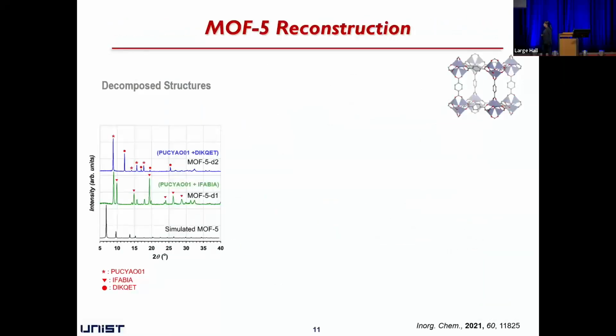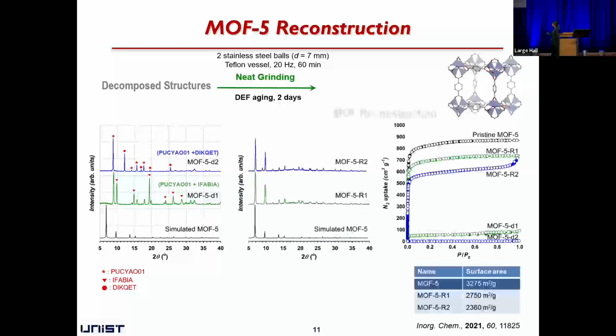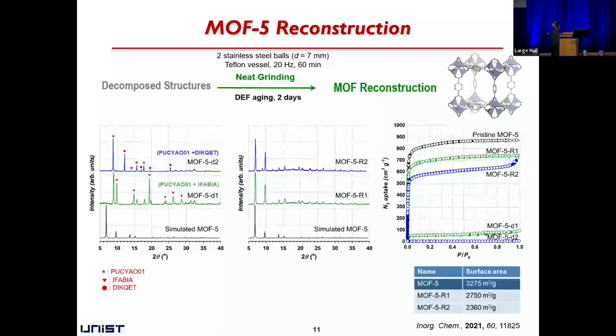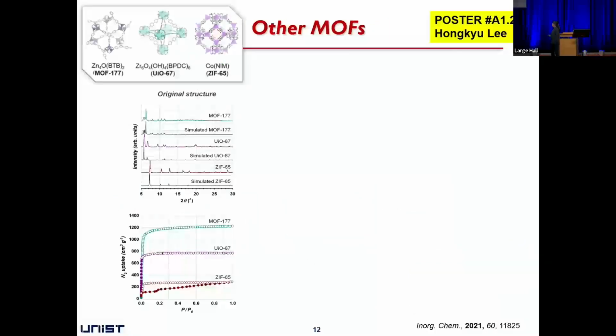So we studied with MOF5 first. We easily prepared the decomposed structure of a MOF5 in 3 different phases, and by just a simple neat grinding and aging in a small amount of a DEF solution, we successfully reconstructed the MOF5 structure like this. We can also extend this method to other types of metal organic framework: mesoporous MOF, zirconium-based MOF, and ZIF.